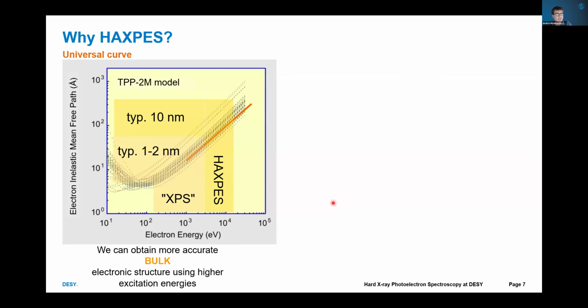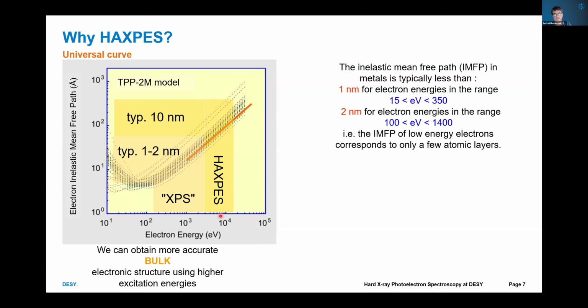So here I have to explain why we are keen on using hard X-rays for photoelectron excitation. For this, you have to look at the universal curve, which describes the electron inelastic mean free path. This means the mean distance traveled by photoelectrons in the solid without inelastic scattering events, depending on the electron kinetic energy.